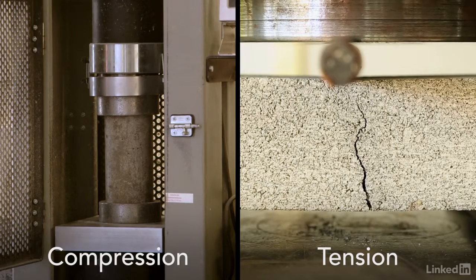Now, again, I can alter my mix designs to increase tensile strength, but even though this is a really important number, we still rarely refer to concrete using that tensile strength designation. We just use its compressive strength. So the reason I'm explaining this is so that you understand that sometimes the reason a designer wants to use higher strength concrete, or go from 3,000 psi concrete in a beam up to 7,000 psi concrete, may really have very little to do with actually needing more compressive strength. They're really just trying to get more tensile strength. We can generally say that concrete is strong in compression, but it's weak in tension. Let's take a look at what we can do about that.